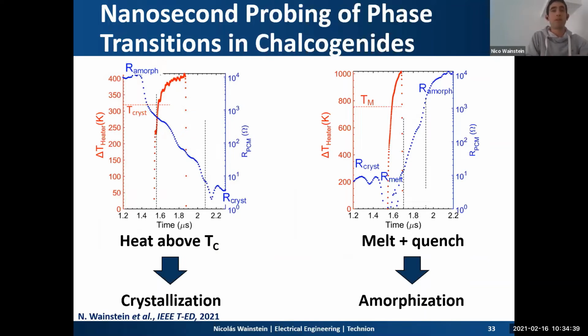So with the proposed setup, for the first time, we can probe crystallization and amorphization transitions simultaneously with the actuation pulse. On the left panel, you can see the crystallization process, where the left axis is the delta T of the heater, and the right axis is the resistance of the PCM. When the temperature rises above the crystallization point, it triggers a crystallization process, reducing the resistance. Hence, with this scheme, we can easily determine the crystallization temperature. Contrarily, as you can see in the right panel, when the temperature rises above the melting point, the resistance reduces to the melt resistance, which is even smaller than the crystalline resistance, and then a fast quench process is triggered, amorphizing the PCM and achieving a higher resistance state.